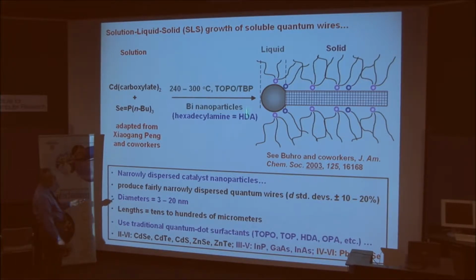Because we can control the size of the catalyst droplets, we can control the diameters of the wire. In fact, our rule of thumb is that the diameter of the wire will be approximately one half the diameter of the catalyst particle. So since we can now synthesize monodisperse catalyst particles of a range of sizes, we can grow quantum wires with a range of diameters. We typically use bismuth. This is the most generally applicable catalyst material, although there are other materials that will work.